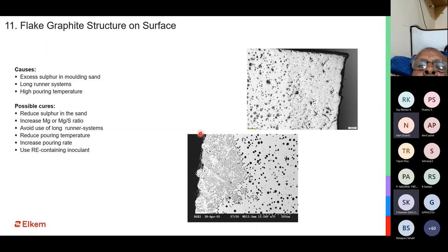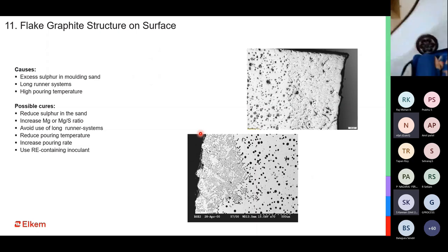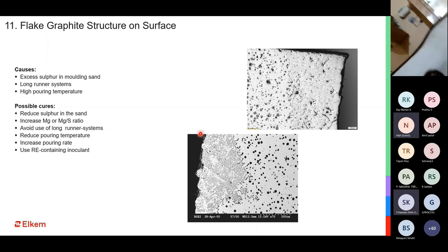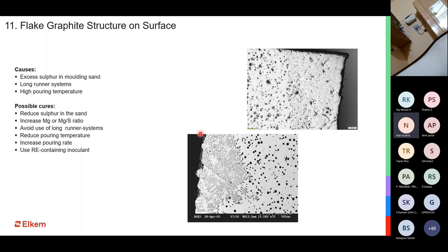But then what will be the optimum magnesium by sulfur ratio for this? You said the remedy is to increase the magnesium by sulfur ratio. Yeah. So what I'm trying to say here is that you have to have sulfur in your metal. The optimum sulfur in the system should be 0.01, and the optimum magnesium should be 0.03.